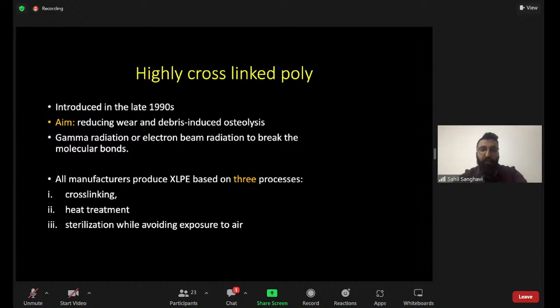Then came the advent of highly cross-linked polyethylene, which was introduced in the late 1990s. The aim of this highly cross-linked poly was to reduce wear and debris-induced osteolysis that we just saw with the conventional poly. This was done by gamma radiation or electron beam radiation to break the molecular bonds. So it mainly depends on 3 processes, that is cross-linking, heat treatment, and sterilization while avoiding exposure to air.